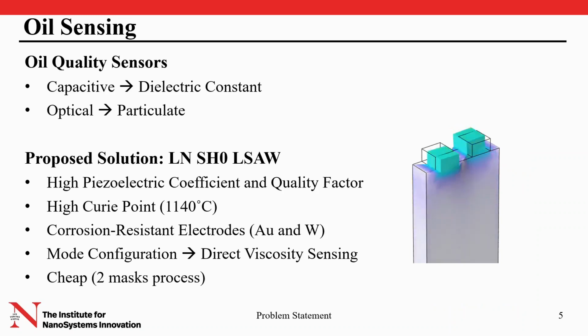As I said at the beginning, our case study is a microviscosimeter. Traditionally, oil sensors are either capacitive and measure the dielectric constant of the oil, or optical to detect the presence of particulate. However, there is no straightforward way to measure viscosity in situ. For this reason, we propose a lithium niobate shear horizontal leaky acoustic wave resonator that leverages high piezoelectric coefficient and quality factor, as well as a very high Curie point.